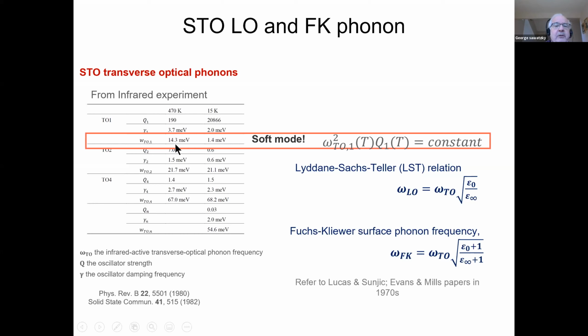Here is the phonon frequency at 470 Kelvin. It's very highly dependent on temperature. This is a transverse optical phonon at 14 milli-electron volts, and it has quite a large width, and it has a huge Q. The Q basically is the static dielectric constant. Okay, that is the oscillator strength, the amplitude of the oscillation. If you go down to 15 Kelvin, that energy goes down to 1.4, it's overdamped, and the Q goes up to 20,000.